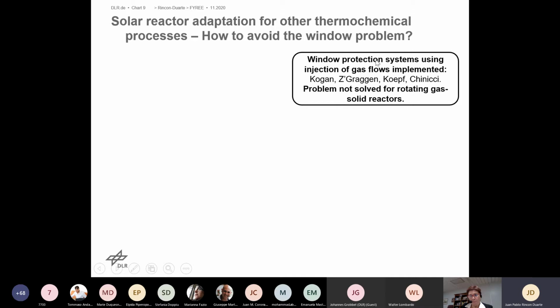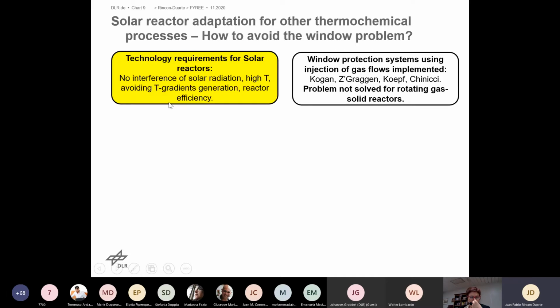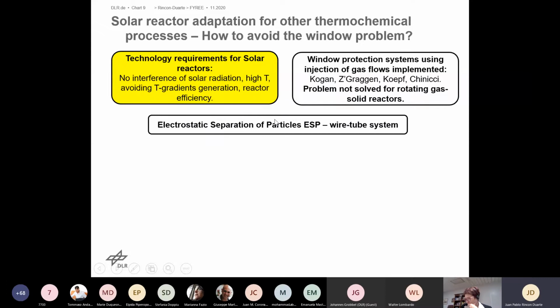This is very well known as the window problem in solar reactors, and it has already been studied by several authors. The most well-known solution until now is the implementation of a system where they inject gas flows in order to create a kind of protection shield for the window. But the problem has not been totally solved until now, especially for rotating reactors where gases and solids are involved. So in our investigation, we are trying to look for a system to avoid this window problem, and considering the different requirements for a solar reactor, we found that the electrostatic separation of particles has a very big potential to solve this problem.